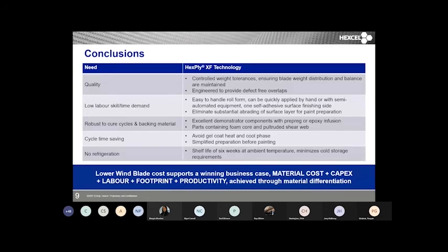So if I conclude, and hopefully I'm not running over time, the needs of your surface for it to be paintable are broken down into 5 main themes. And Hexcel XF technology has been developed, proven and launched to hit good quality, because you're controlling the weight, your tolerances, and your distribution in balance in your manufactured blade. If you saw the layers of the XF going down in the animation, you may be concerned that the overlaps would be a source of defects that needed work. But Hexcel has formulated the resin and the architecture of the system, so actually it's engineered not to give overlap defects.